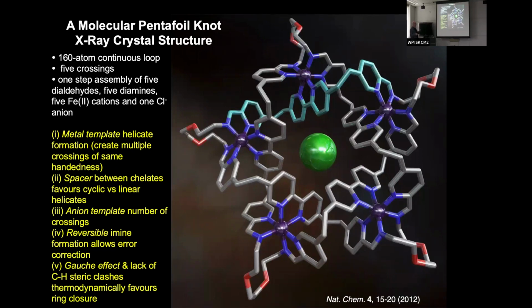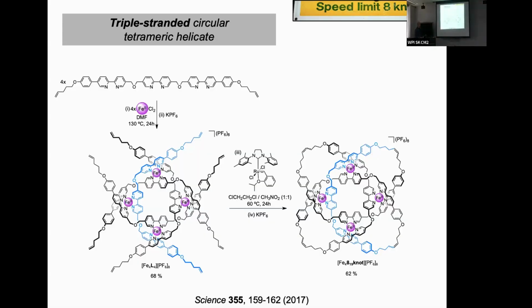O-CH2O interaction leads to something called the gauche effect, a stereoelectronic effect that actually favors this gauche conformation around here, which favors, again, this curvature in this chain, which favors ring closure. So there's a lot of different design elements that feed into this assembly process. But having developed that, we can apply those techniques to other kinds of knots.